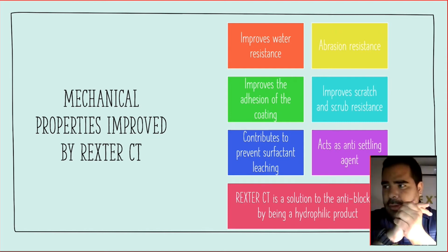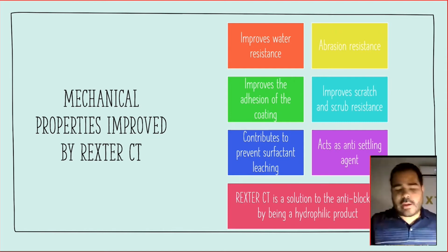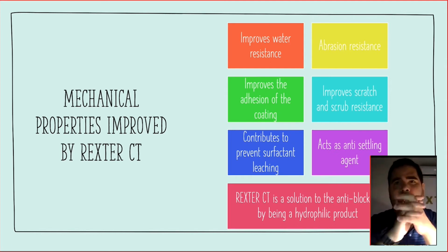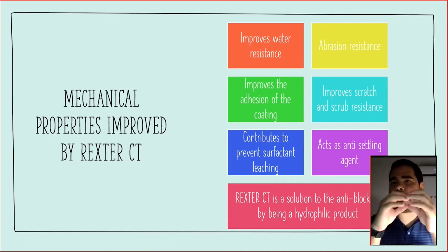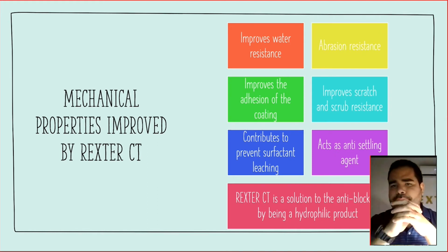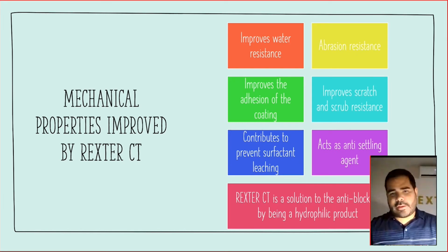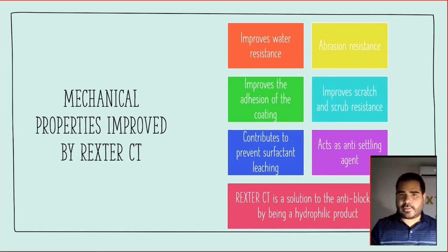You mean by loading, dosage? Correct. Yeah, we recommend actually to use Rexter CT... This is a very interesting question because our recommendation is usually from 5 to 10% maximum. However, this will also depend on factors like the type of PVC the paint has, because we have customers who get really good, very impressive results with 3%, and some customers use 5%, others use 3%, and others go to 7%. So it depends on adapting to each case, but our recommendation is always 5 to 10% loading into the formula.